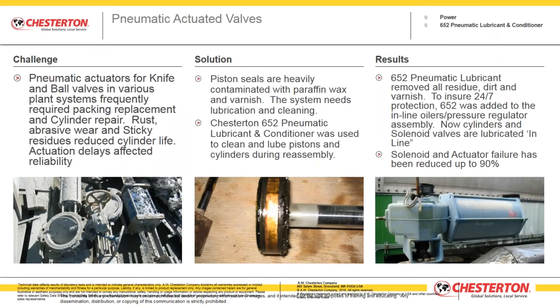We take a look at the buildup on cylinders, for example, in the center picture on the case history. We can see what we're talking about is that paraffinic waxy film. And properly lubricated, we've seen conditions where we went from 200,000 cycles on the actuator to over 4 million cycles on an actuator simply by using some enhanced lubrication.